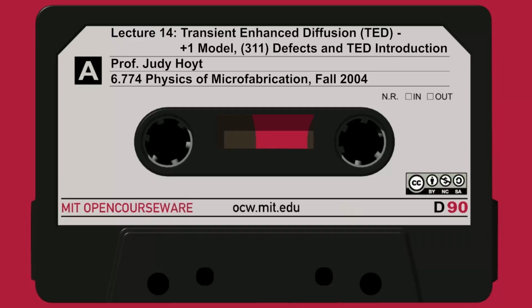Then the only thing you're left with, you still have single crystal material, is down just below the original amorphous crystal interface. You are left with what's called end-of-range damage. It's a series of dislocation loops and other sort of extended defects that don't anneal out. End-of-range damage in general, unless you were to melt the sample or do something, is something we most of the time end up having to live with to a certain extent. It's very hard to get rid of. But the amorphous layer is gone, and we have single crystal silicon. So it's just a reminder when we're talking about amorphization and a process for restoring the crystal to its single crystal nature.